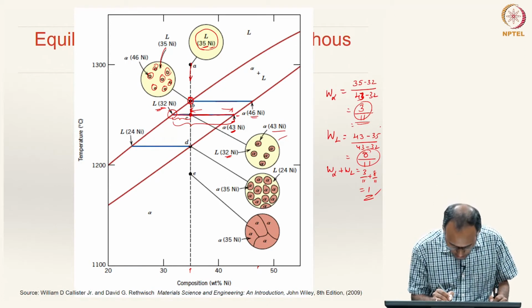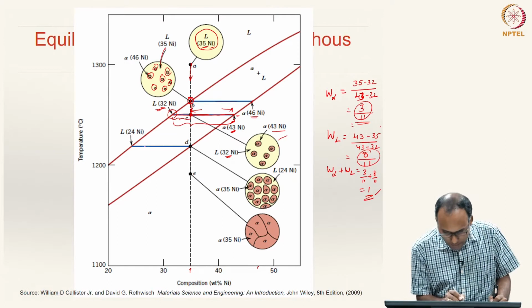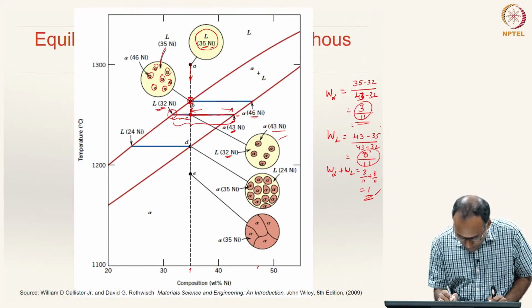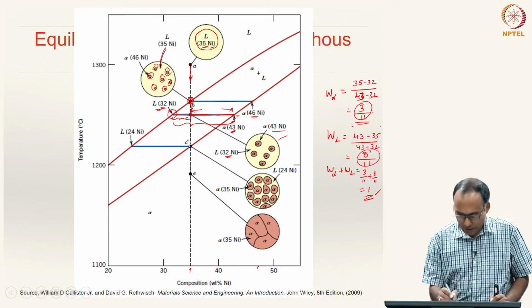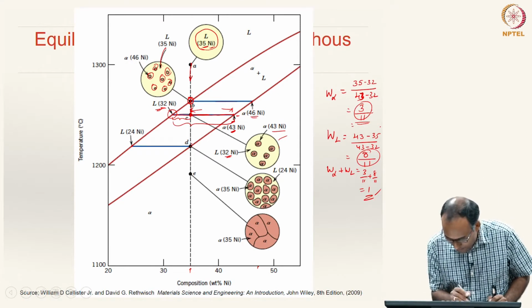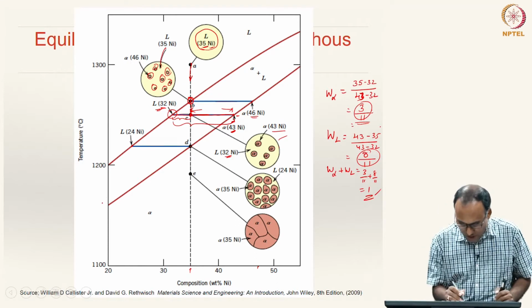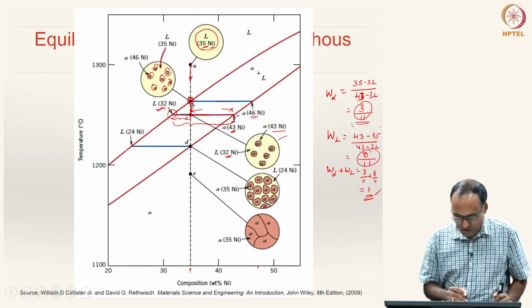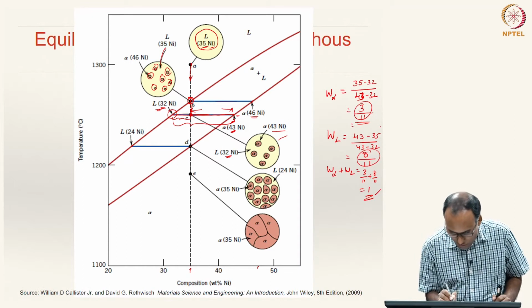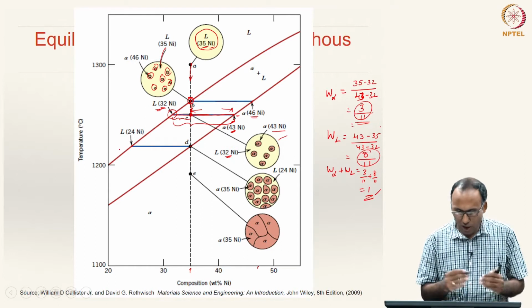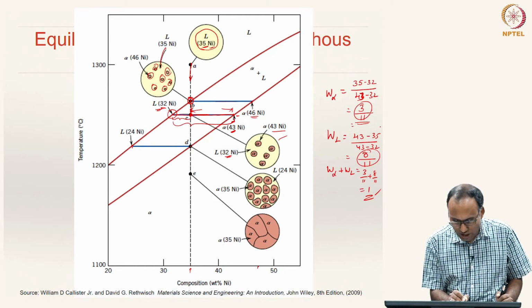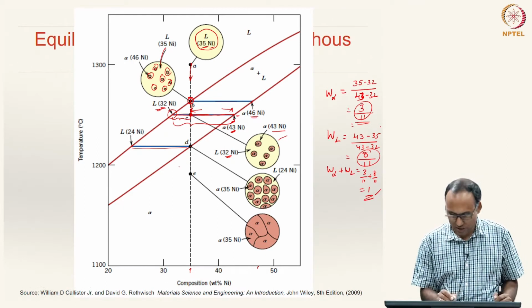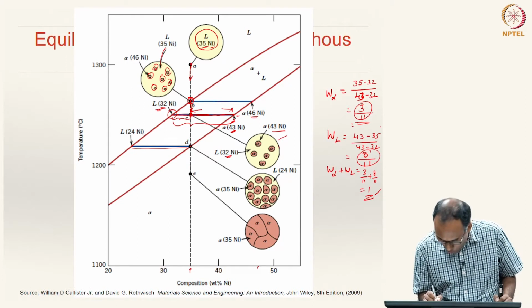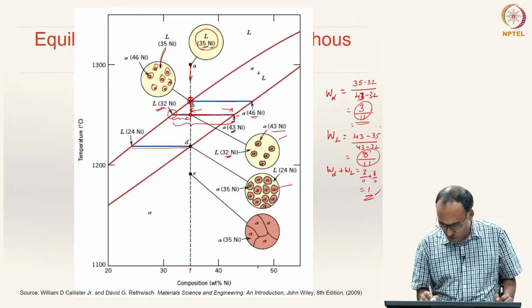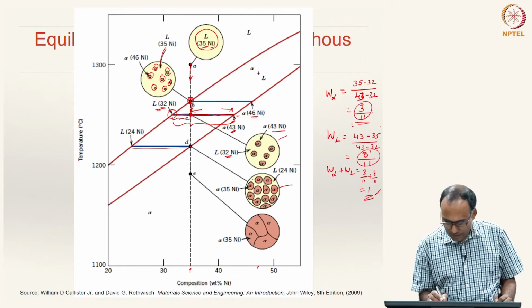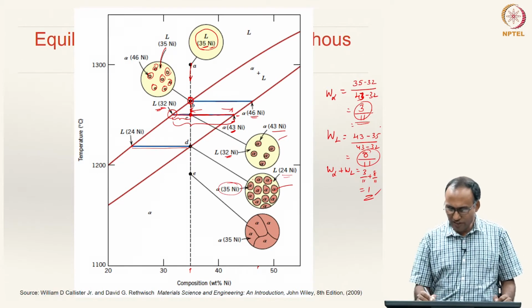And now, if you further cool it down just above the solidus line, again you are in the two phase region, and then you can see that it hits the liquidus at 24% nickel and the solidus is hit at 35% nickel. That means, at this particular configuration, what is the weight fraction of the solid? The weight fraction of the solid is, so this is the point, right, and all the liquid. So, from that point to the distance to the liquidus line, that is the distance. So, it is almost 100%, very close to 100%, just above this line. So, you have several alphas, the solid solutions, and some amount of liquid is remaining. Whatever alpha is remaining has already got 35% nickel and the remaining liquid has got 24% nickel.